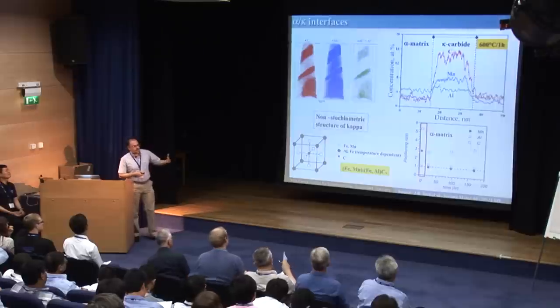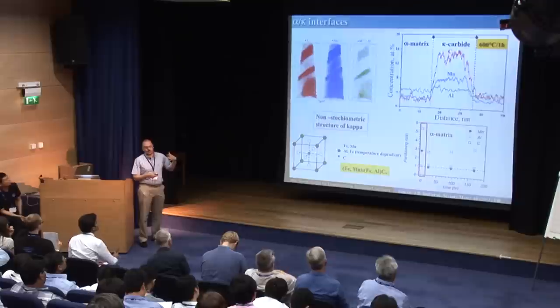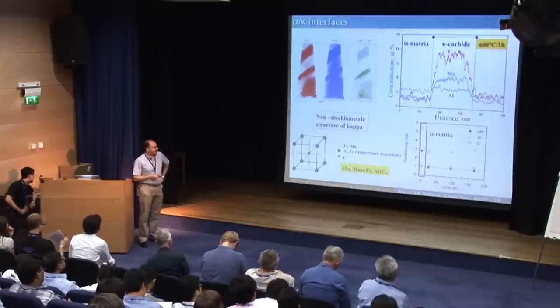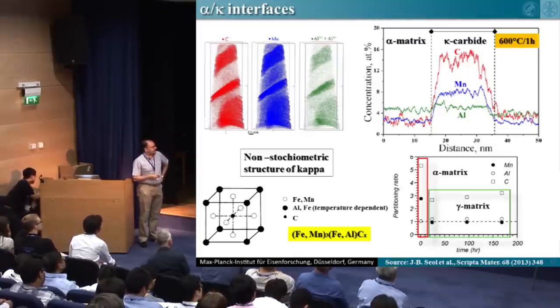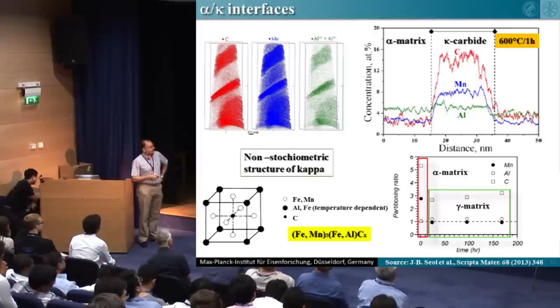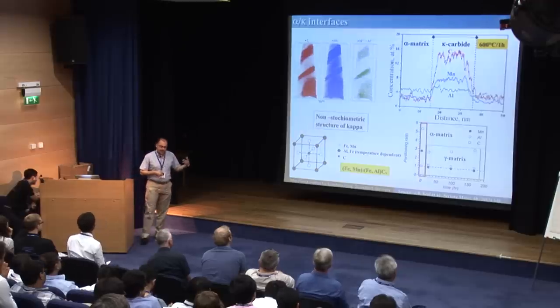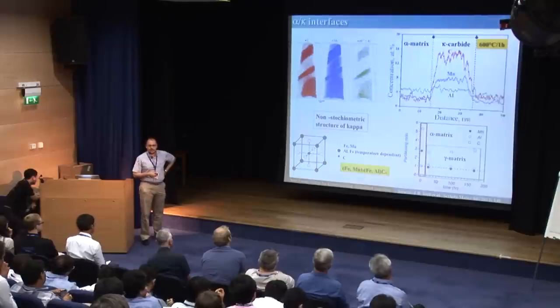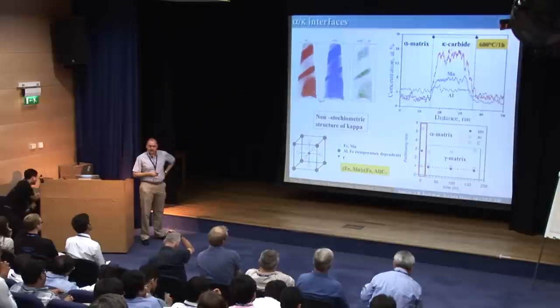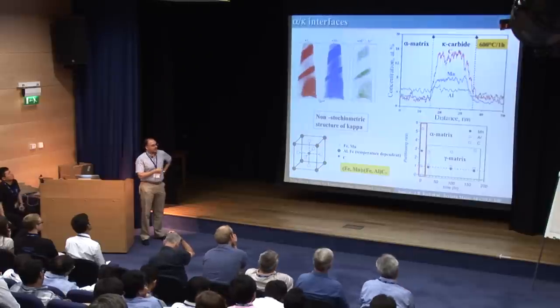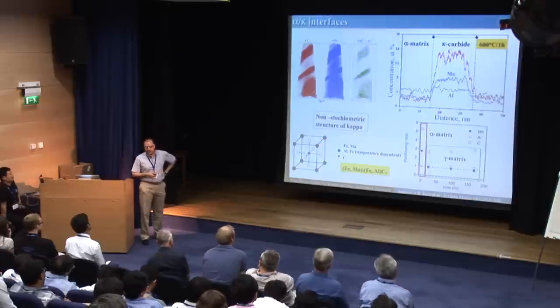Of course, if we compare the partitioning behavior of the different alloys, it's a bit different here. In the ferritic matrix, you can see the partitioning behavior of carbon is 2 times higher than in austenitic matrix. And manganese is also partitioning to the kappa with respect to the austenite. So this gives us an understanding of the deformation of coherent kappa phases in the austenitic matrix with respect to semi-coherent, incoherent kappa phases in ferritic matrix.